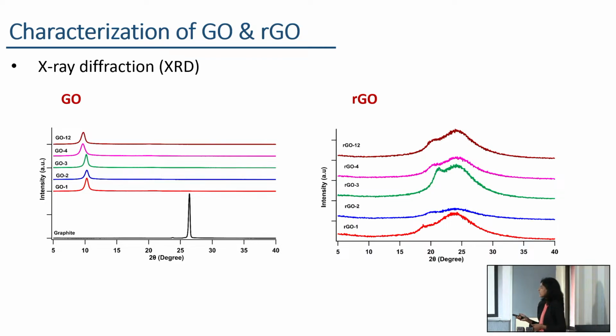When it comes to the XRD spectra of these GO samples, we can observe a new peak at lower angles around 10 degrees, which corresponds to the 001 plane of graphene oxide. At the same time, in these spectra we cannot observe any diffraction peaks at around 26 degrees, corresponding to the 002 plane of graphite. That means this graphite has been completely oxidized into these GO samples during the oxidation process.